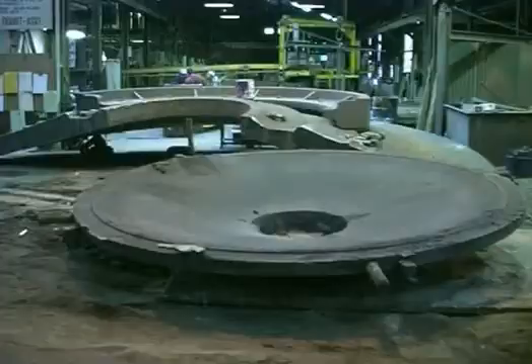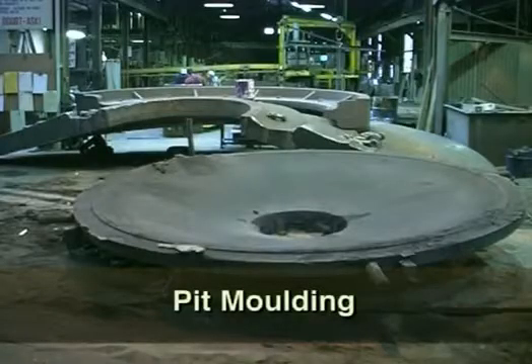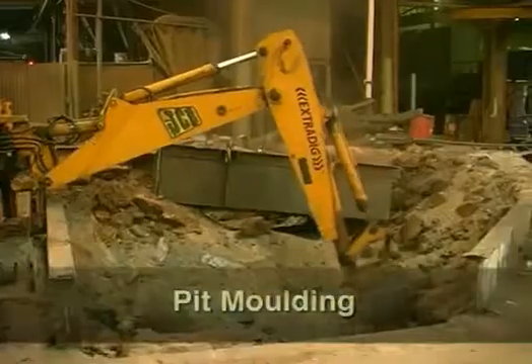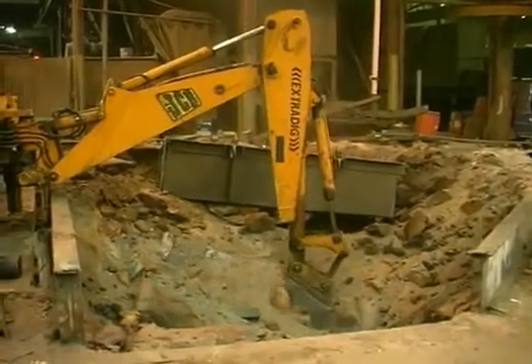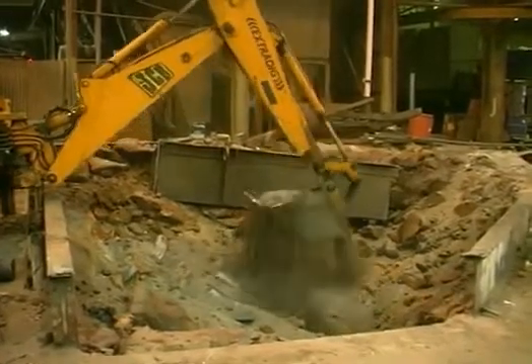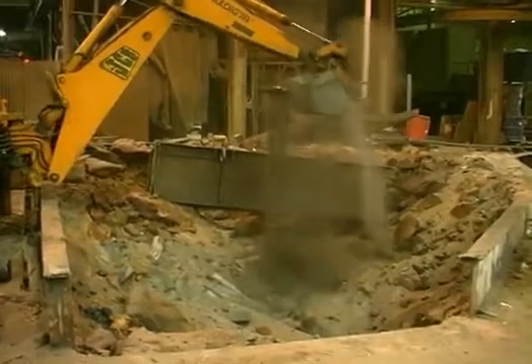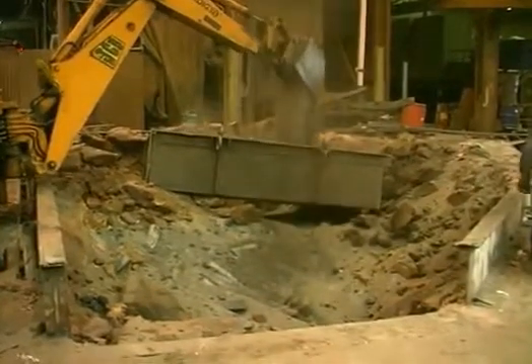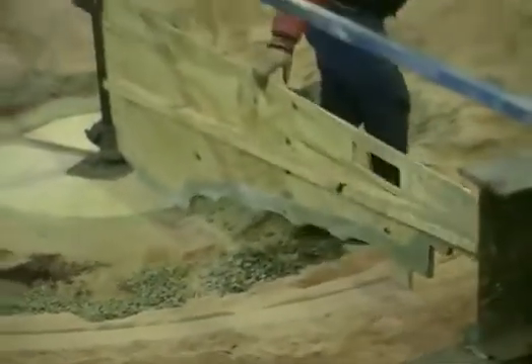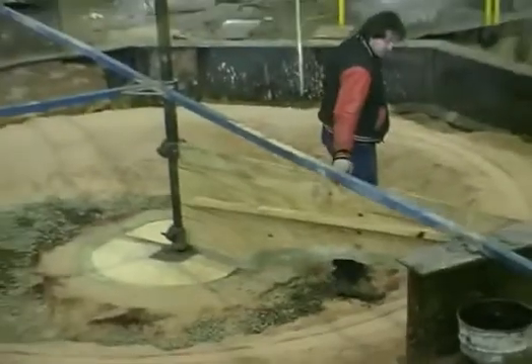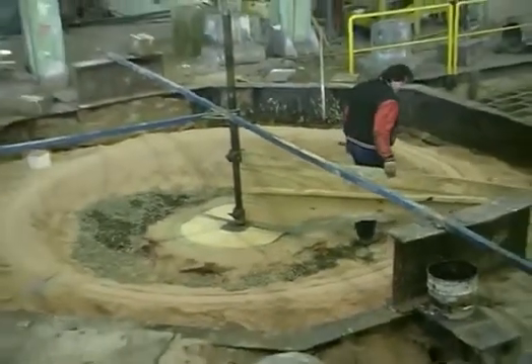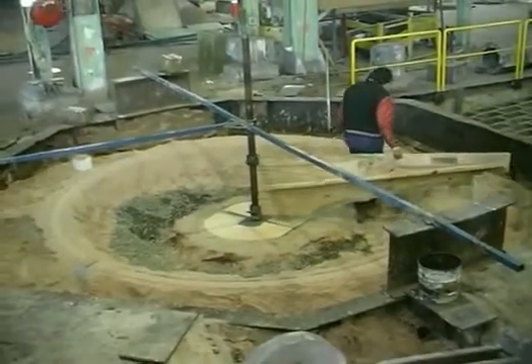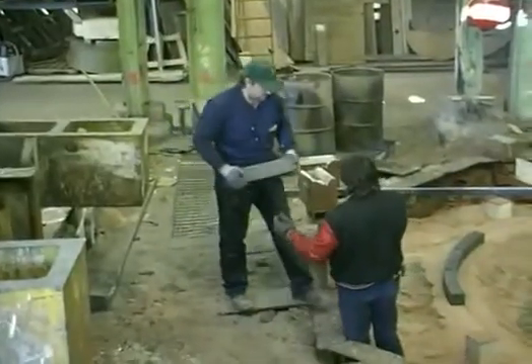Small numbers of this type of very large casting are manufactured by the pit moulding method. To make this type of casting, the first step is to remove the rubble from the previous casting. Approximately 50 tonne of sand will be used in producing a 40-tonne casting. Self-setting phenolic resin bonded sand is swept to shape, first using the outer end of the strickle board.